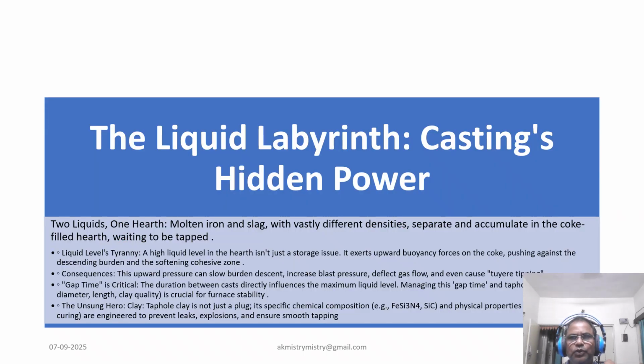Now, we are coming to the next slide. Once iron and slag are molten, they drip down through the coke and collect in the furnace hearth. But tapping these liquids is a complex, delicate ballet. The sheer volume and level of this liquid in the hearth have a profound hidden power over the entire furnace. A high liquid level creates immense upward pressure, pushing against the coke, the burden, and the critical cohesive zone. This can disrupt gas flow, slow the descent of new material, and even cause furnace damage.